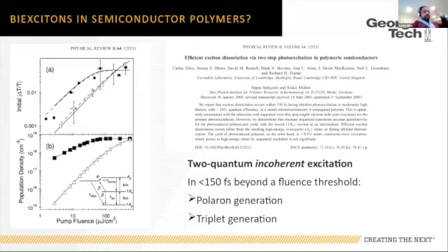If we go to the Wannier exciton limit, this is very well defined. We can find with linear spectroscopy very well-defined signatures of Wannier biexcitons. We can quantify binding energies. We know what the relationship of biexciton binding energies is, let's say in gallium arsenide quantum wells, with respect to the exciton binding energy, and it's very well defined. We can identify them and measure them. Not so in organic systems with Frenkel biexcitons.